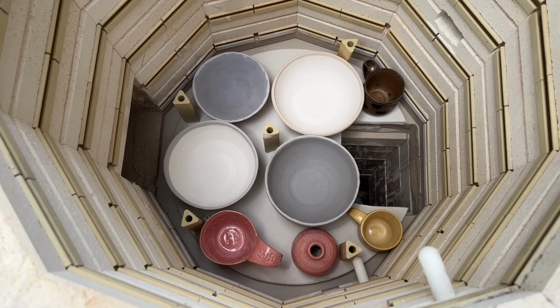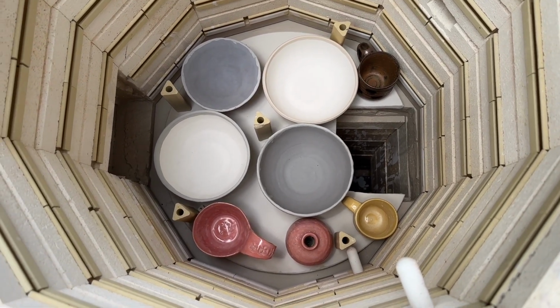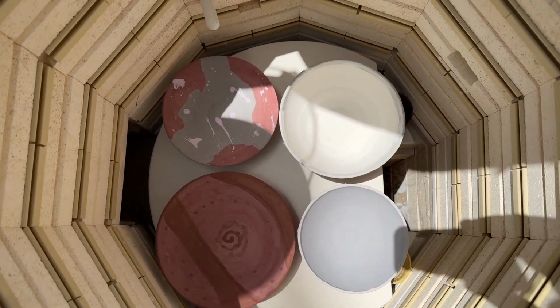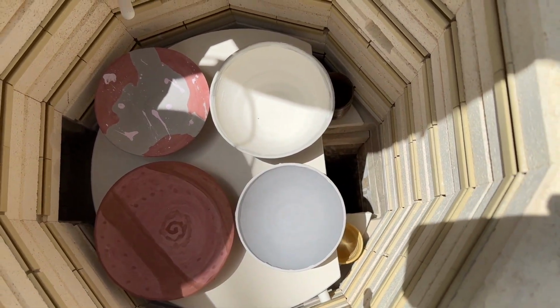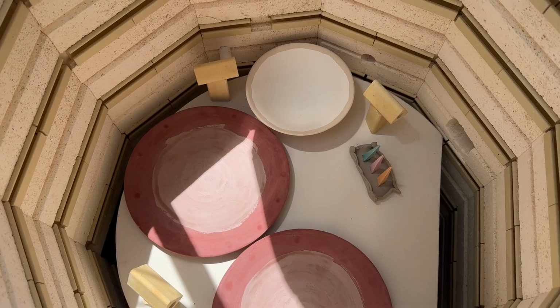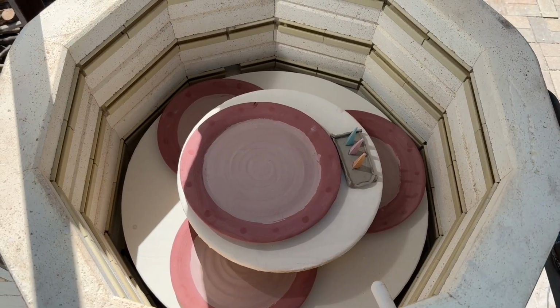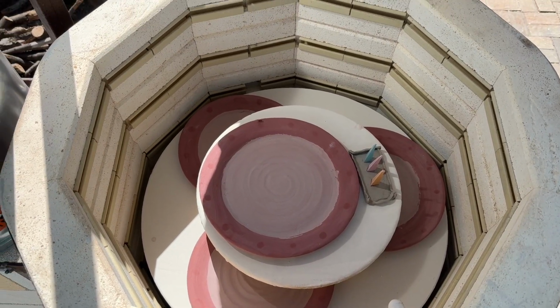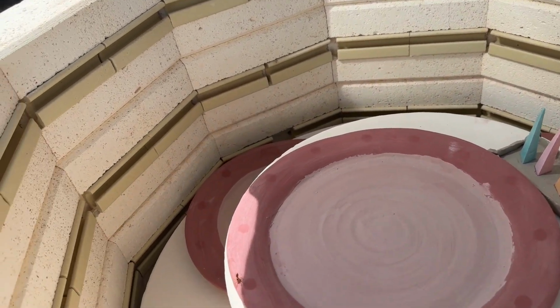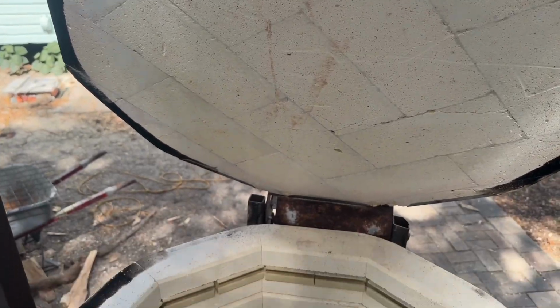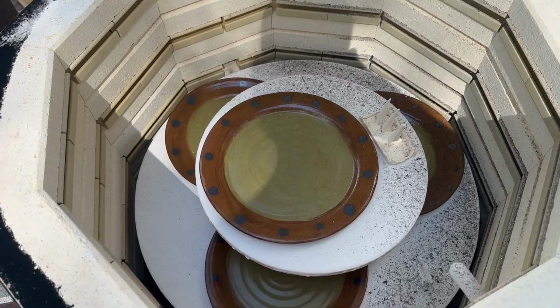This first shelf, I loaded up bowls as a bag wall, and the temperature came out pretty good. The second shelf came out a little bit hot. The third shelf was just about perfect. And the top shelf, I didn't get enough heat up there. When I did the bisque fire, it was the opposite. The top was 300 degrees more than the bottom, so there's going to be an art to stacking this kiln.